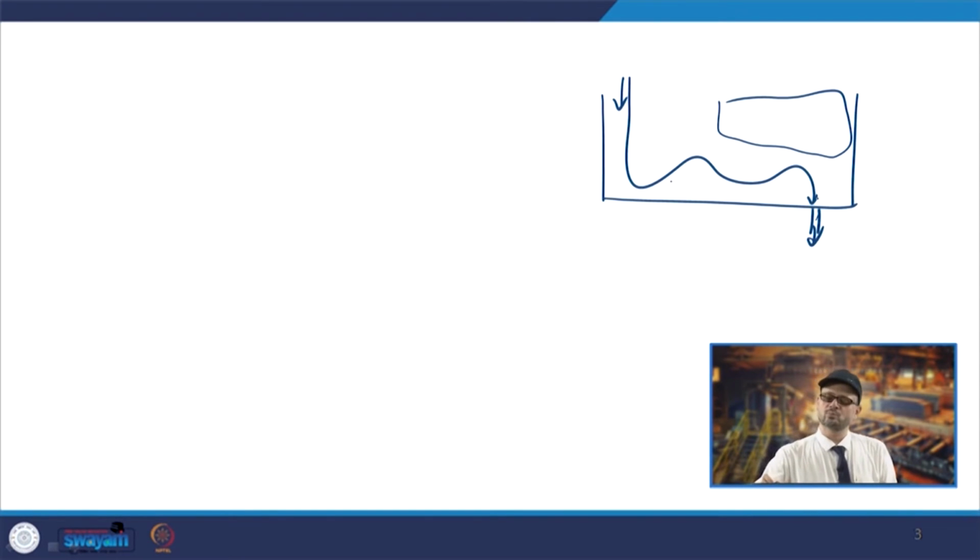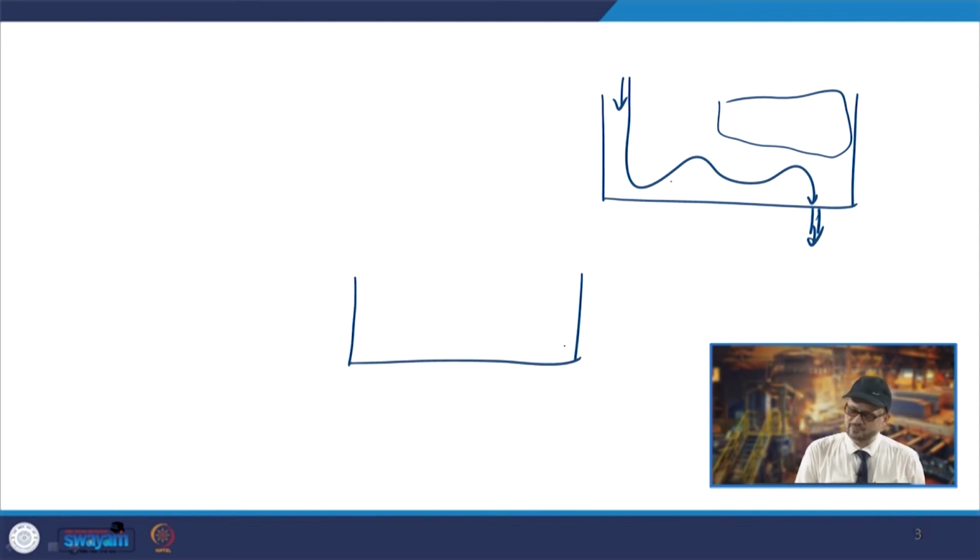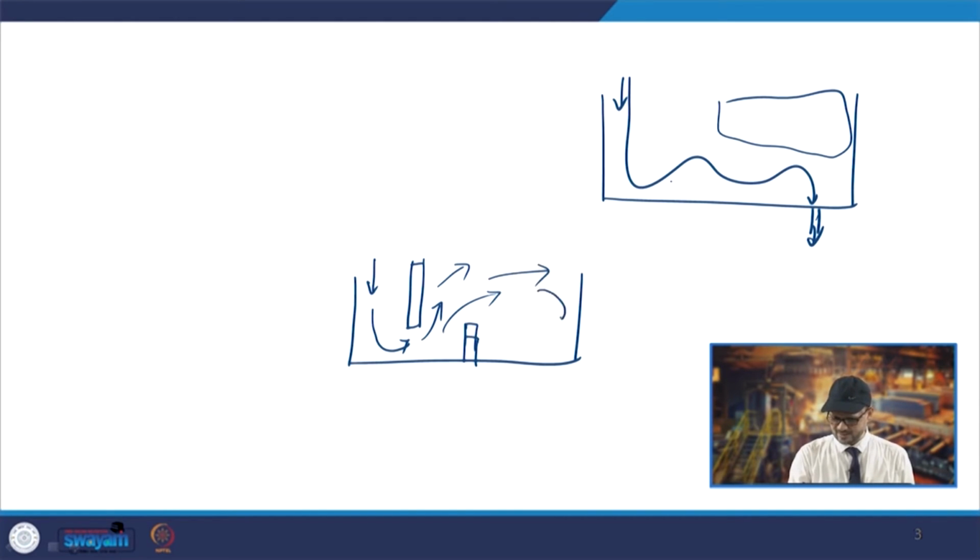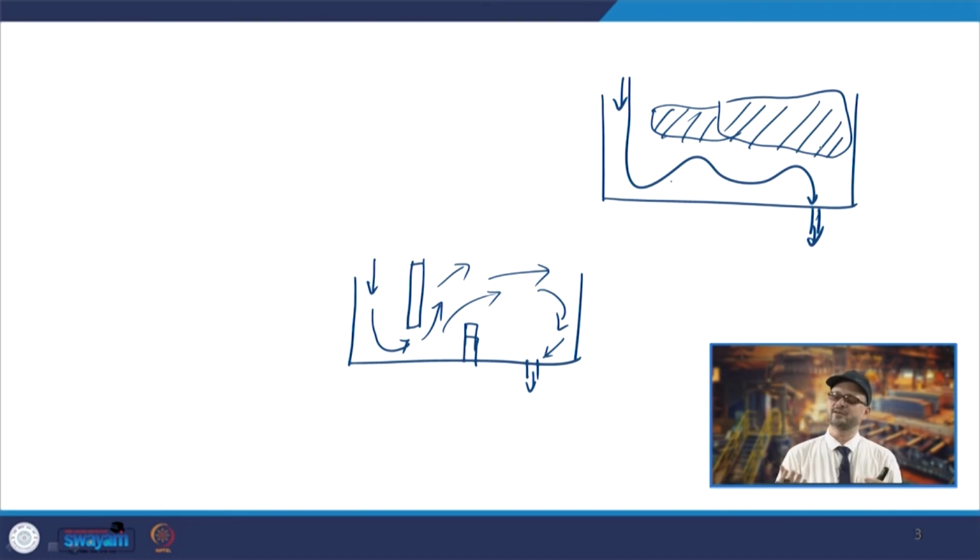and then it will be coming out. So, what we do normally is we use these tundish furnitures. Many a times, you have inlet from here, so we use different tundish furnitures like here, then you may use the dam here. So, the metal which goes will be coming up and then it will be moving in this direction. Now, from here it will move like this, and if suppose it is of this height, from here it will go even in this direction, and then from here it will come out, and you have outlet here. In this case you have many zones, all these zones which are like a dead zone. Now, you can see that by the use of these tundish furnitures like dams or weirs, you are effectively utilizing all these places.